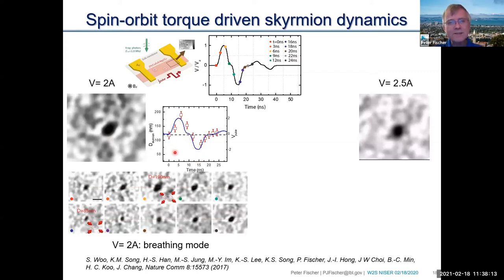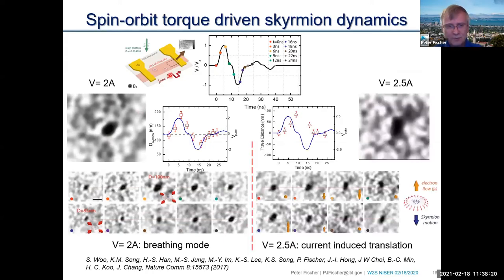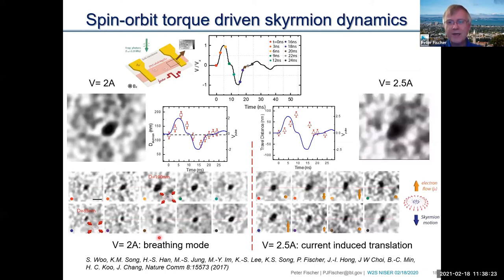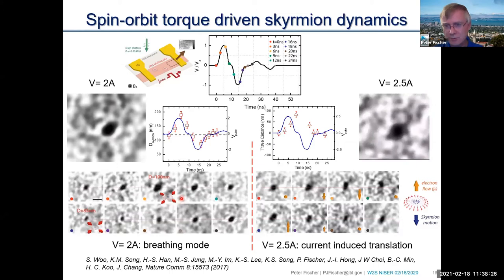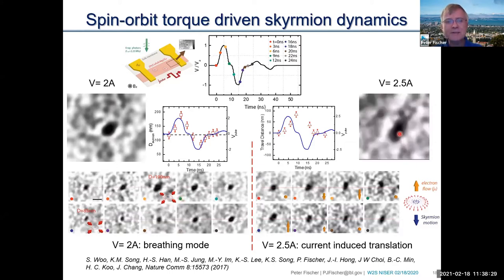But what was interesting is that when we increased the amplitude of this excitation pulse, the motion changed. It went from the breathing mode, which was going up and down, to more of a current-induced translational motion. So what we were able to show in this paper is that by adjusting the amplitude of the excitation pulse, we can modify on demand the dynamic response of this skyrmion. That means the nanoscale spin texture responded in a very specific way to our driving force. And I think this is an interesting opportunity, because it allows us to study skyrmion dynamics in detail with time-resolved X-ray microscopy.